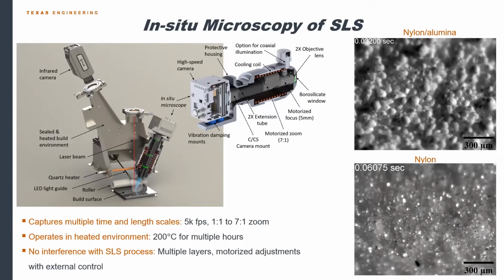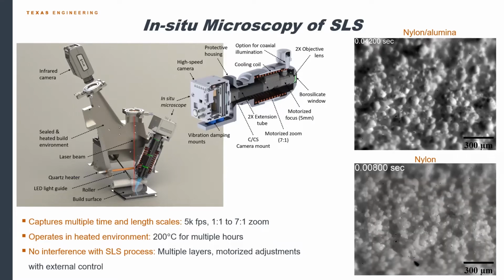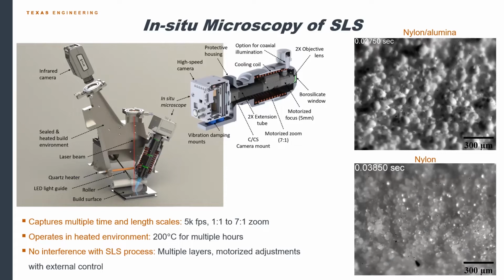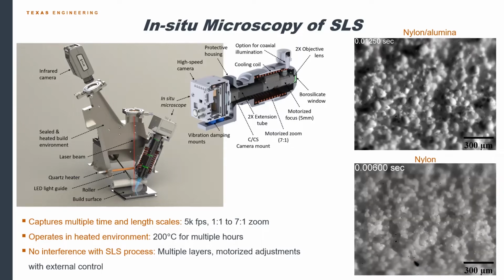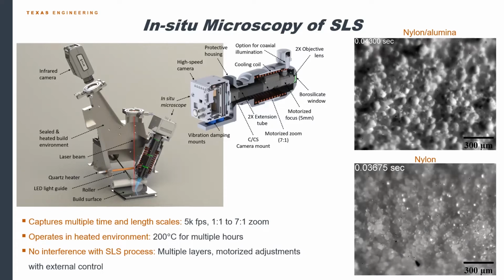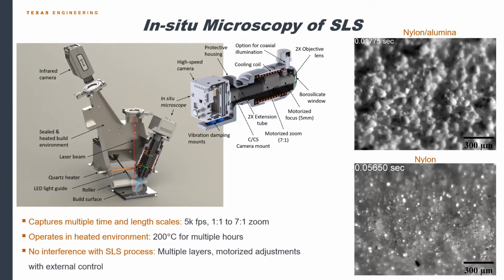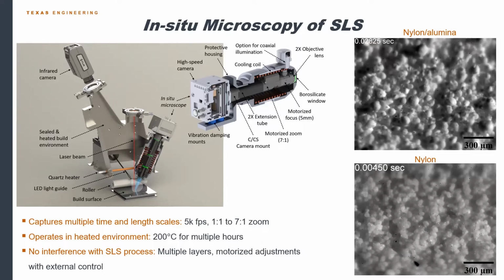The video on top is scanning the mixed powder, nylon and alumina, at about 1,000 millimeters a second. The white circle, which is kind of faint on the screen, represents where the laser is at all times. The bottom video is just plain nylon. In the top video, not much is actually happening. In the bottom video, after the laser passes, the particles become translucent, which is indicative of melting, and then they start to coalesce. This led us to a new understanding that the powders behave differently during laser sintering, and we developed a model to describe that.